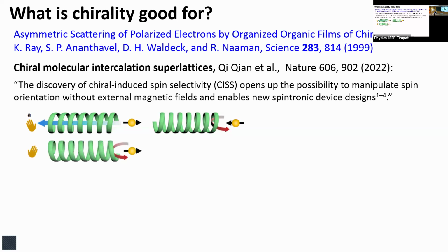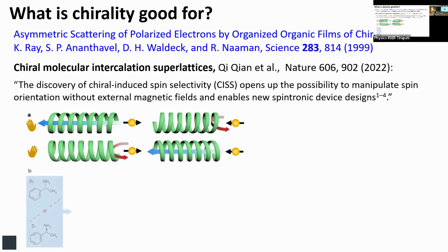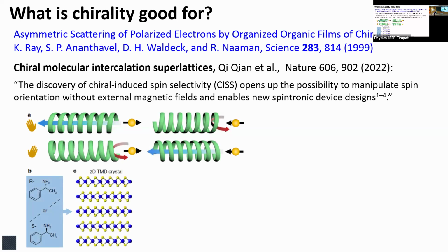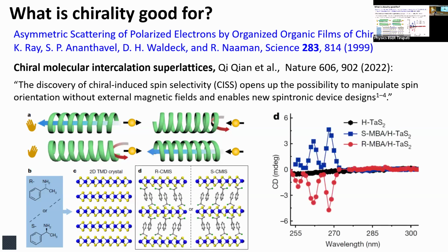And then if you reverse the chirality, the situation gets reversed. And this is what they did in this paper. They took the same molecule and intercalated it in tantalum disulfide, which is a two-dimensional crystal. There's a van der Waals gap, and you can squeeze in these molecules here. And once you squeeze in only one chiral molecule, the system would be chiral, because chirality cannot be averaged. Even if it is randomly going, it will be chiral. And so they made that system, and then they looked at the optical property. The way you detect chirality is by doing an absorption experiment twice on the same material.